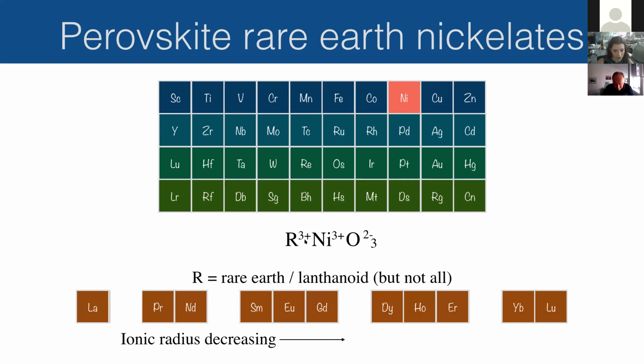And what you have is a 3+ rare earth ion and a 3+ nickel ion, which is actually rather unfavorable for this nickel. So sometimes it's quite difficult to grow these materials. But what you see is that along the lanthanoid series, because the atoms are getting heavier because you're adding more electrons, protons, neutrons, but also the ionic radius is decreasing. So they get heavier, but they get smaller. And this is because the Coulomb interaction between the nucleus and the electron cloud is getting stronger. So you have the ionic radius, which changes along the series. And as I showed before, for the Goldschmidt tolerance factor, this is very important and determines the structure of the material. It changes the bond angle and thus the physics.